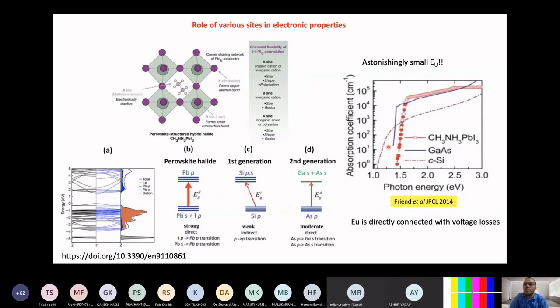If you compare now MAPbI3, you find MAPbI3 is as good as gallium arsenide in terms of the energetic disorder. A semiconductor with very steep absorption at the absorption edge is a very clear-cut signature of the quality of the semiconductor, and that is directly connected to the voltage losses in the solar cell devices as well.